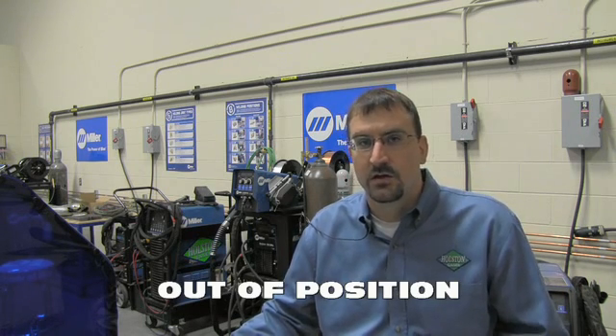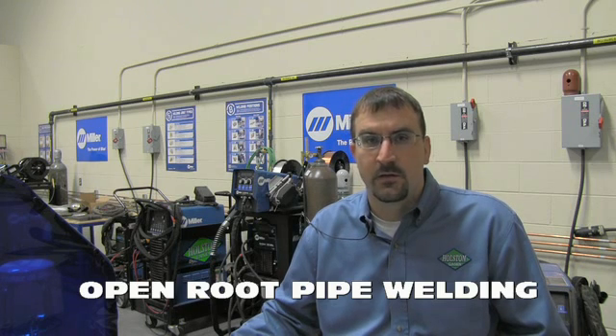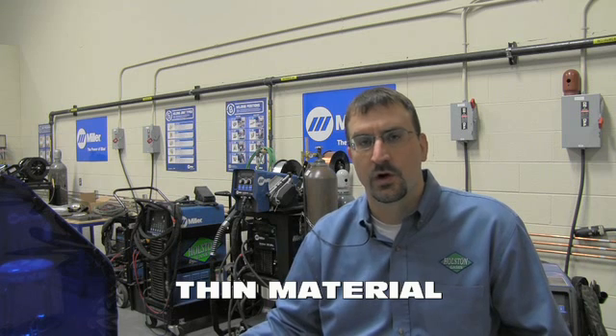So during this film, you can see that the wire shorts out, a small explosion occurs, spatter is generated, the arc opens back up, and then it shorts out, and opens back up, and shorts out, and does this cycle, like I said, 60 to 300 times per second. Because the arc extinguishes is why this is a low heat input process, and is why you can weld out of position, you can weld over gaps, it's good for open root pipe welding, and it's really good for very thin material, sheet metal or car body work.